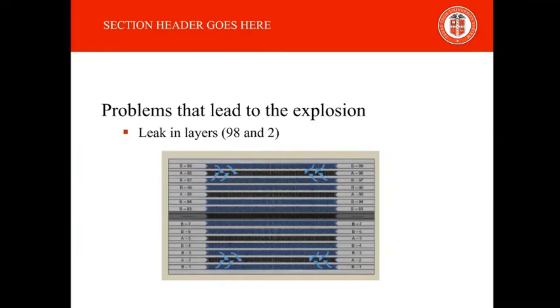In September 2015, HETSCO, a third-party service provider, repaired interpass leaks in the outermost layers of the exchanger. There was a leak in layer 98 and layer 2, as you can see in the figure. So they decided to weld the inlet and outlet of layers 99, 98, 2, and 1 shut, and leave layers 97 and 3 open to the process.